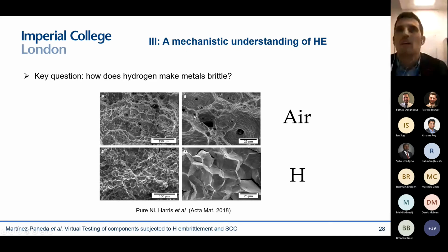So you can see here, right? In the absence of hydrogen, you see these very microvoid-driven ductile fracture processes. But suddenly, the moment you introduce hydrogen into the picture, what you see is very brittle fracture processes with hydrogen accumulating in the grain. Well, with hydrogen basically making these grain boundaries weaker, or cracks propagating through the grain boundaries. So how can it be? What is this intergranular fracture process? What is happening that triggers this?